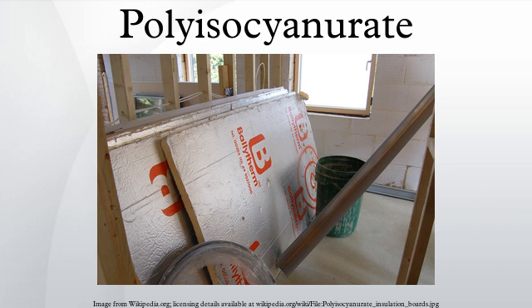This isocyanurate polymer has a relatively strong molecular structure because of the combination of strong chemical bonds, the ring structure of isocyanurate, and high cross-link density, each contributing to greater stiffness than found in comparable polyurethanes. The greater bond strength also means these are more difficult to break, and as a result a PIR foam is chemically and thermally more stable. Breakdown of isocyanurate bonds is reported to start above 200°C, compared with urethane at 100 to 110°C.